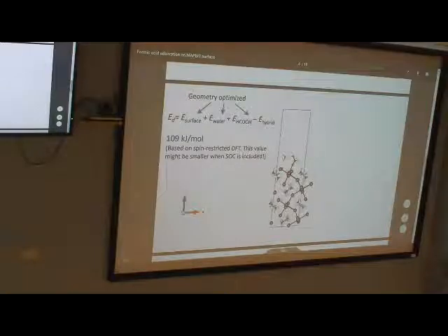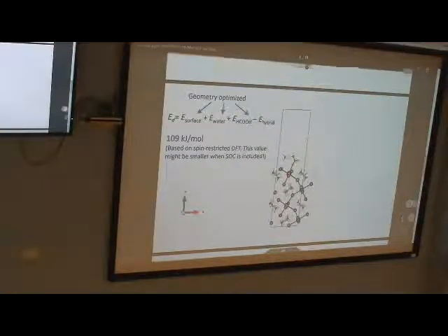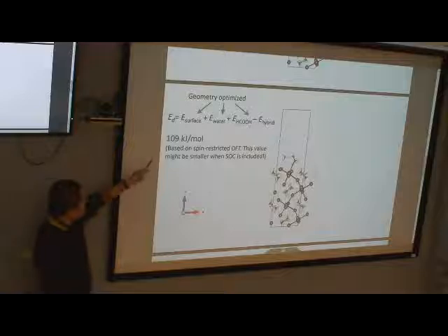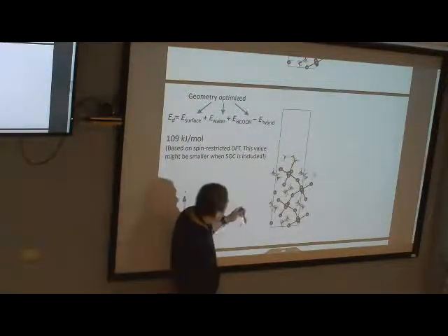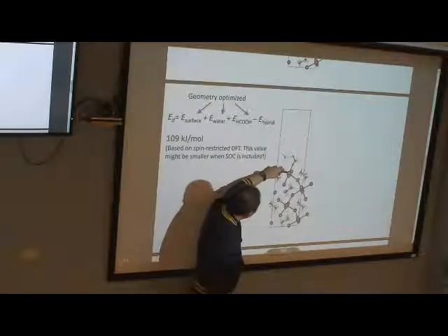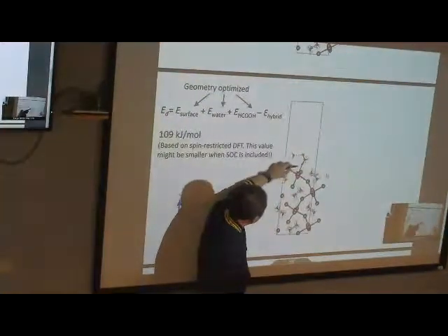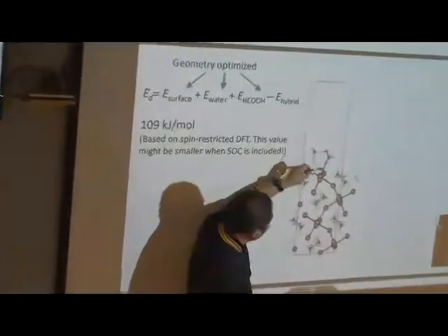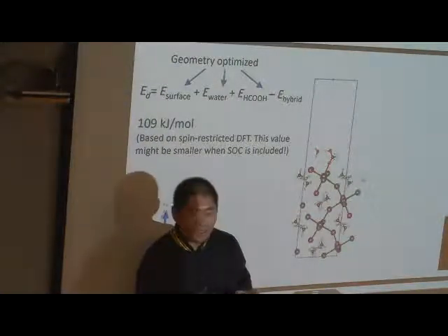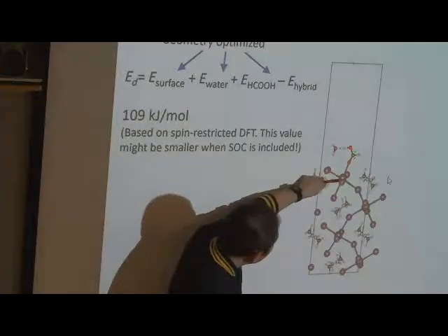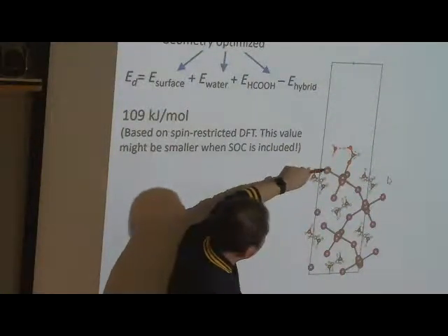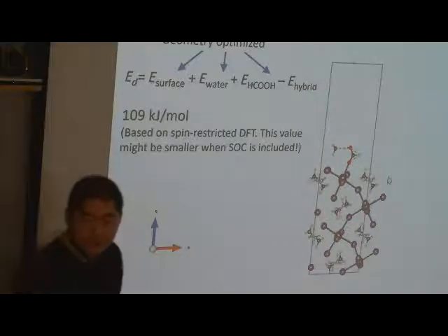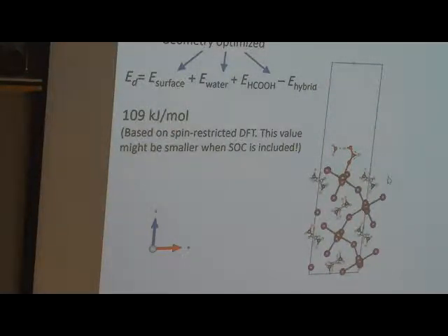Next I tried putting water. And this is very, very stable, I guess. The binding energy is like 110. Here, we still have the oxygen metal bonding, and this is the water. So it forms a ring structure. This is one member of the ring, this is one atom, second one, third one, fourth, fifth, and sixth. That's the reason why this geometry is very stable.